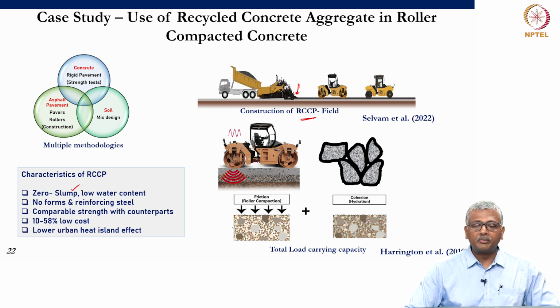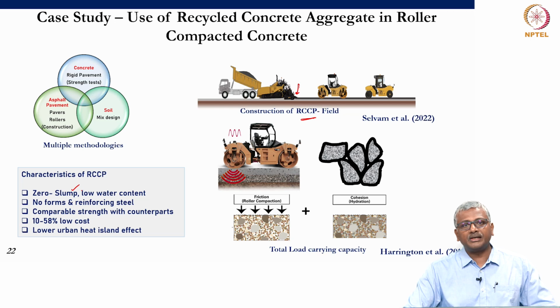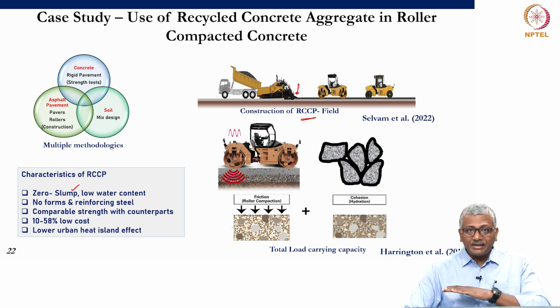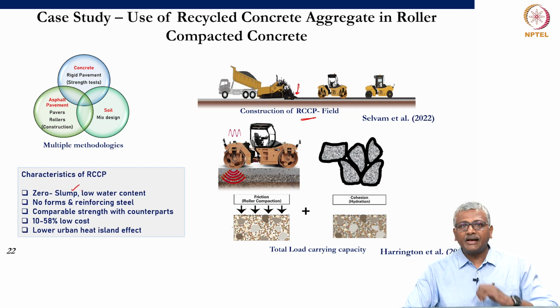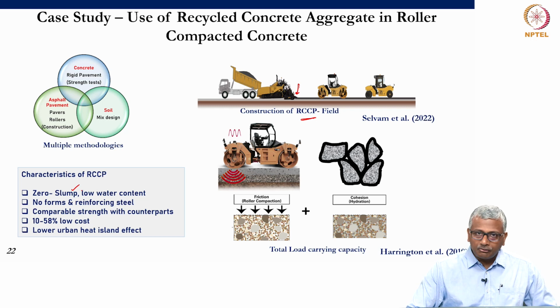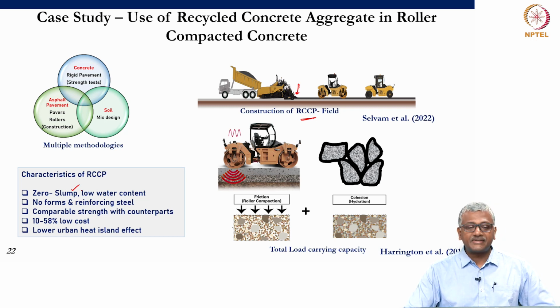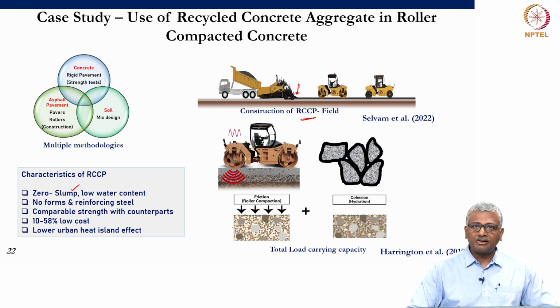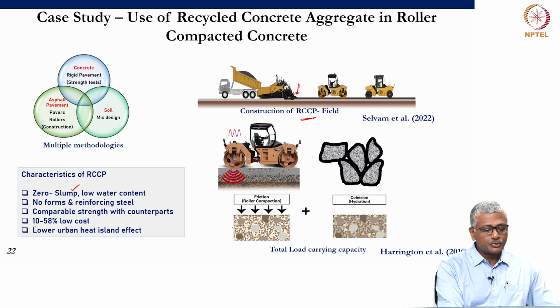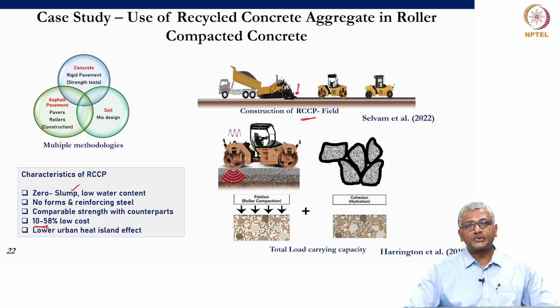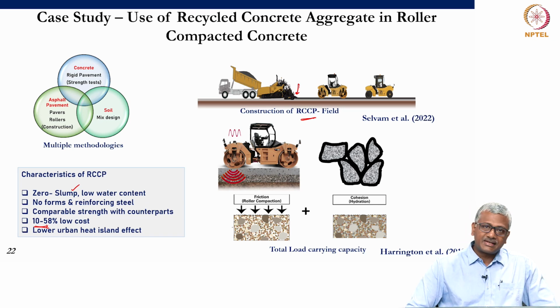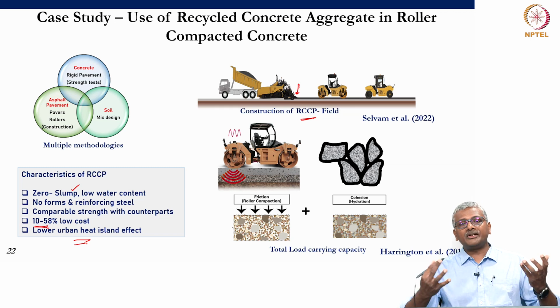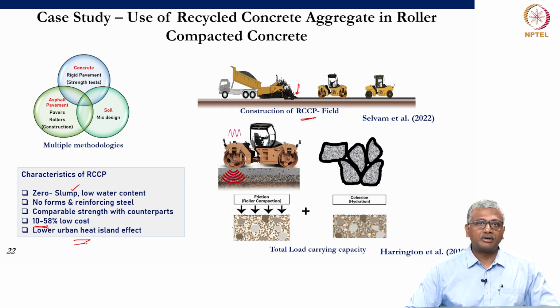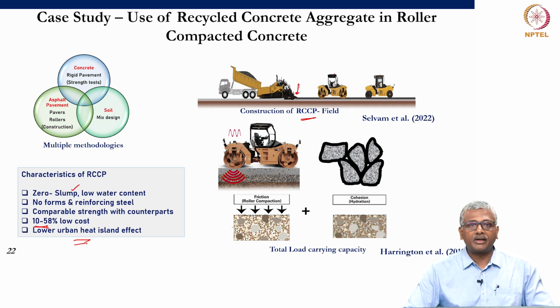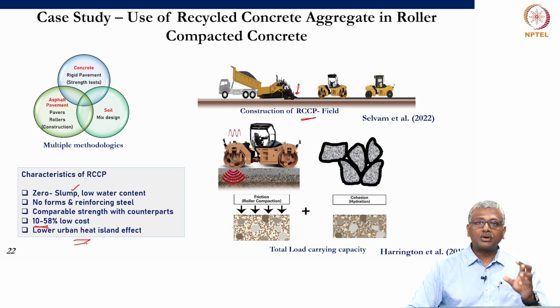Typically, even the cement content is quite low because you don't really need so much cement to produce the workability. You just need to control water to cement ratio to get the strength, but the entire concrete is getting compacted to a very high level of densification, okay. There is typically no reinforcing steel in such concrete because you use it for applications like pavements and dams, okay. And you can actually make it strong enough because of the kind of compaction process that you give. And because of using lower cement, you are obviously going to be reducing the costs significantly. And because there is less cement, there is also going to be less of heat emanation from the concrete. Okay, so, there is a lot of advantage of roller compacted concrete pavements as opposed to typical concrete used for pavement quality construction.